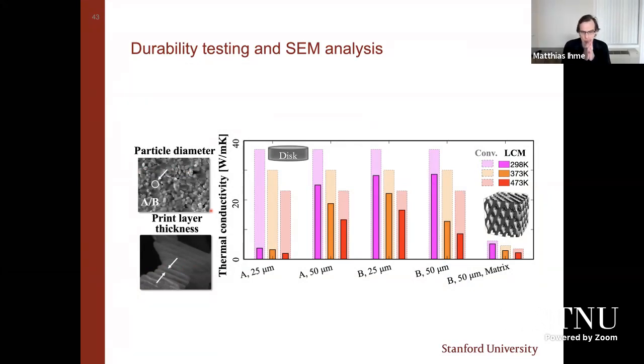Another property that is critical is the thermal conductivity. How fast are we conducting heat through this pore structure? Here we explored the feasibility of using different sinter materials and different pore diameters, which is illustrated by these parameters A and B. Depending on the pore diameter, we can control the conductivity.